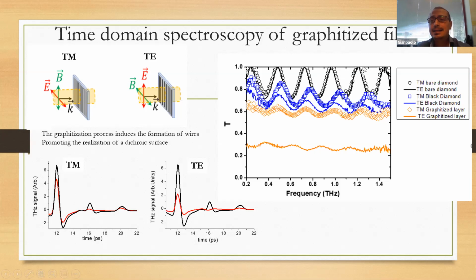The dots represent the TM polarization, so when the field is perpendicular to the wires, and TE when it's parallel to the wires. Of course, the black ones represent the bare substrate and there is no change. The blue one represents the black diamond, that is the sample where the graphite has been removed, but the ripples still provide the dichroism of the sample. And the orange curve is what we have when we measure the two polarizations of the graphitized sample. And it is quite interesting. It's comparable with some other results in literature. And now we are working to increase, of course, this change in order to realize optical devices.